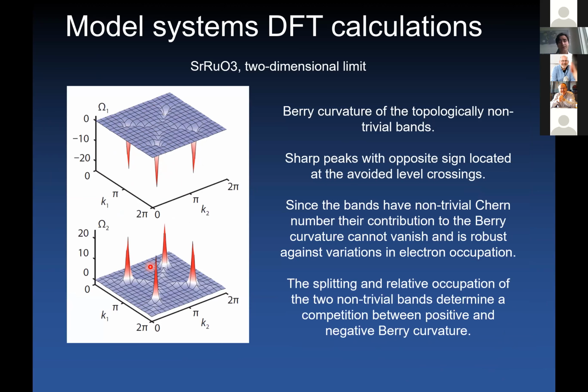And also very important is the fact that these level crossings occur between topologically non-trivial bands. So these are robust against variations of electron occupations. So no matter where your Fermi level is located, and depending on impurities, you will still have these topological points. And the relative occupation will determine whether you will observe in a transport experiment either a positive or a negative Berry curvature.